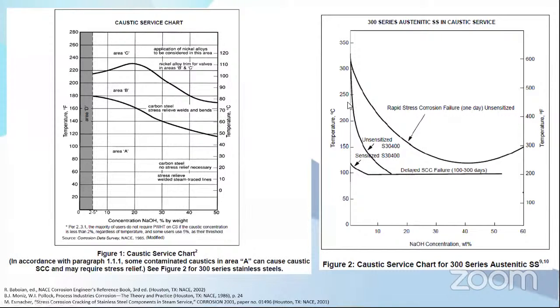Stainless steel is the same. Sometimes it's even worse than carbon steel. So if you upgrade to stainless steel, it doesn't affect the cracking resistance very much. You can see in the 30% caustic, the maximum temperature is 100 Celsius. It's not very different from the post-weld heat treated carbon steel. It has just a little bit higher resistance, but not a lot. The one that has significantly higher is nickel alloys.